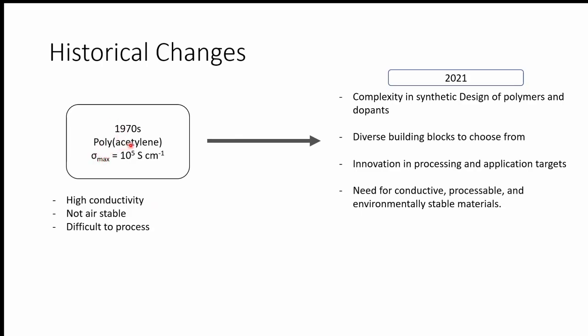However, when this was reported in the 70s, although it had high conductivity, it was not air stable. So you need to handle it under a very specific environment. And the other thing is that it is difficult to process. So if you're trying to make it into a stretchable, foldable interface, that would not be possible because it's very brittle.